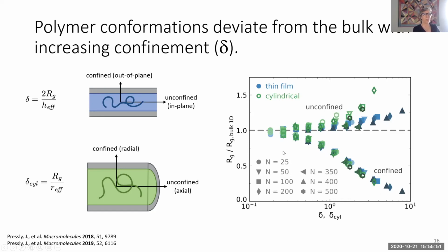In the confined direction, we were surprised to find that the extent of the collapse of the polymer chain was the same for cylinders and thin films. And as you go out to a confinement parameter of 10, you squeeze that radius of gyration in the confined direction by about a factor of 10. And then in the unconfined direction, so that would be in the plane of the thin film or along the cylindrical axis, we see that the distortion of the chain conformation is more pronounced in the cylinder than it is in the thin film, which is the blue data. And that's pretty understandable from the geometry of the system.